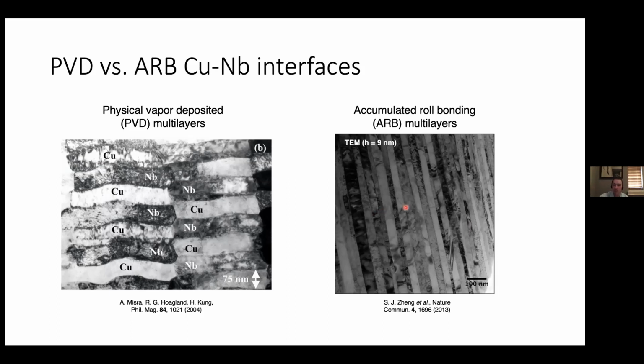You end up with a very well bonded, very high perfection multi-layer composite like the one that you see here, right? So these are both metal laminates. The difference is that they're made by different processing routes, and the fact that they're made by different processing routes results in different crystallographic characters of the interfaces that form between these copper and niobium layers.